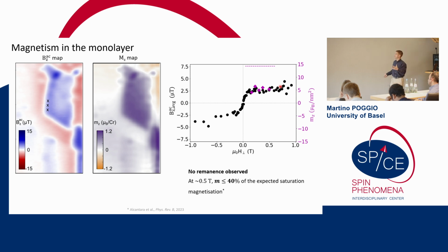So this is, say, an initial indication that perhaps the long-range order in this monolayer is being suppressed by the fact that it's a 2D system. We can't be sure that it's not for other reasons, but this is a good indication. Another indication is that we find no magnetic remanence at 0 field. Okay, so there's essentially no measurable magnetization when we go to 0.